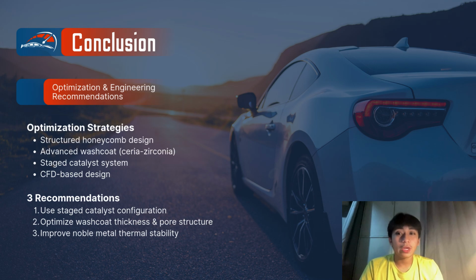Now, for conclusion, to address these challenges, optimization strategies focus on both structural and material improvements. Structured honeycomb designs reduce pressure drop while maintaining high surface area. Advanced washcoat materials such as ceria-zirconia improve oxygen storage capacity and thermal stability. Modern vehicles use a staged catalyst system, a close-coupled catalyst for fast light-off and an underfloor catalyst for complete conversion. Computational modeling is also used to optimize flow and temperature distribution.